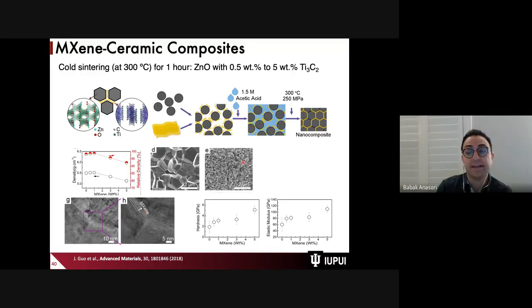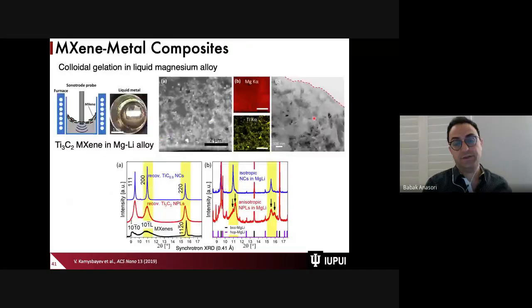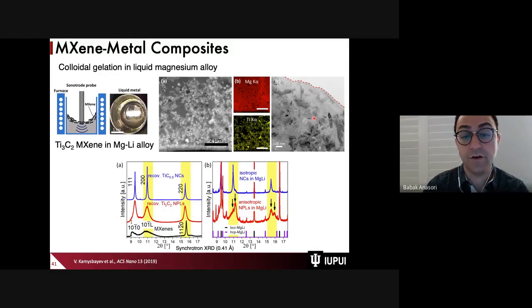At the same time, we can have a uniform distribution of the reinforcement in the matrix, because it's not just random particles in the matrix. We can have it wrap around different particles. So we have a uniform distribution. And by having these layers, we can not only improve the strengths, we can also improve toughness because of crack deflection. So we are combining all the benefits by using these MXenes instead of just adding particles to hope that we can improve the strengths of the material. So that's the area for composites more related to mechanical engineering.